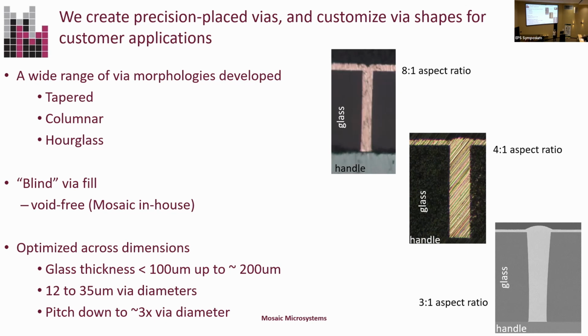The trick, of course, as anybody knows who's tried to fill vias, is that those have to be void-free, and that is what we've developed, is a void-free fill. And these are over glass. We tend to concentrate on 100 micron glass up to 200 microns.